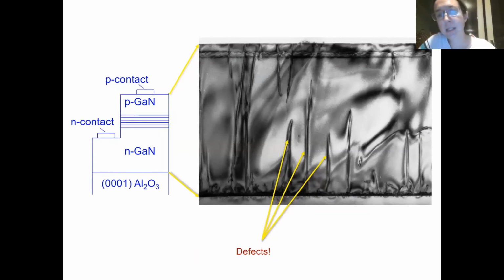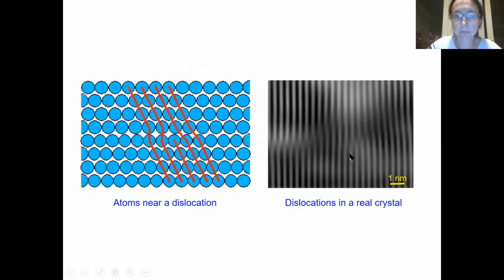Okay, so I said that there might be other fates for my electron and hole, my positive and negative charge carrier, if I didn't get them to recombine quickly. And those fates relate to these things: defects, mistakes in the crystal. This is another transmission electron microscopy image of a real LED. It's quite a simple one in this case, but we can see that there are these great lines running through the crystal. And this is a picture of the mistakes that might be in the crystal.